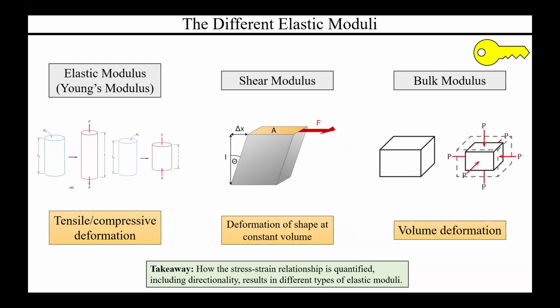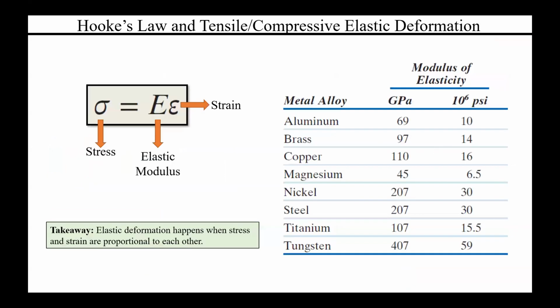If one side of the material is changing its volume deformation faster than the other, then in reality you don't have one bulk modulus for the entire material. You would have to break the material up into segments, and you would have a bulk modulus in this portion and a bulk modulus in this portion. And the reason for that is that the material changing in different ways depending on where in the material you are means that there are different structures within the material. So you would need a bulk modulus for each structure that you were actually looking at.